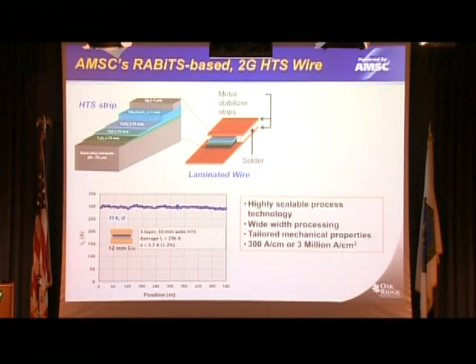So this is their configuration. As I mentioned previously, we have 3 buffer layers. They have the same configuration. They have a superconductor, and they can make this wide. They can make the superconductor thicker. And as I mentioned to you, here's a plot of 0.5 kilometer of tape with a current carrying ability of 300 amps, which translates to 3 million amps per centimeter squared. So very good properties over length.